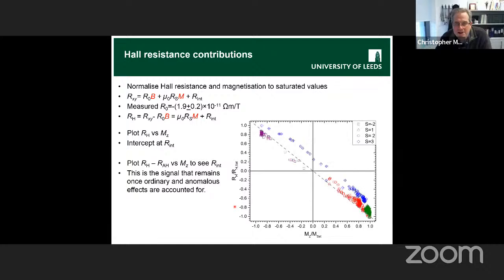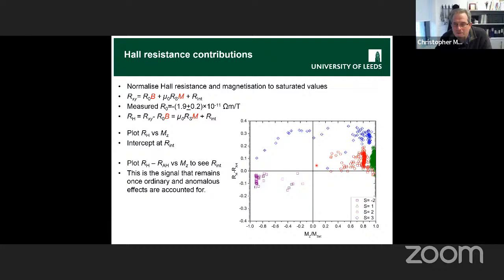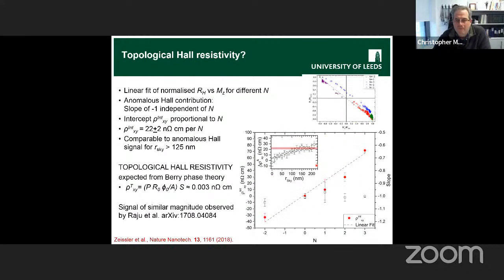So let's take all our data, put it on this plot. The green data are the ones that we saw before, but now we've also got red, blue, and purple for different winding numbers. And we're comparing to this grey dashed line for anomalous Hall effect only. So we can subtract that off. And then if we look at the average level within each of these groups of points, this is what you get.